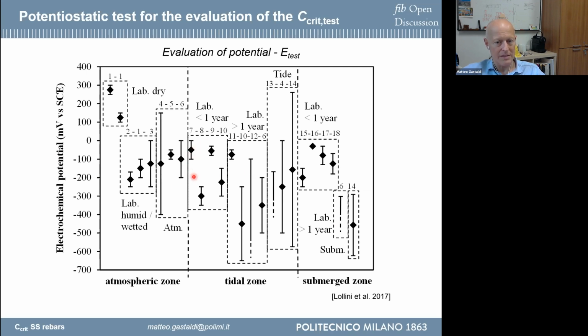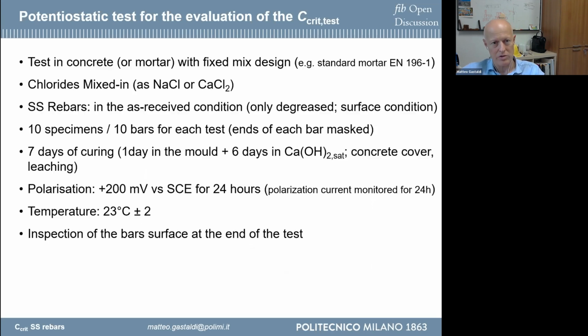We can analyze the data related to the potential on real structures, and you can observe that in a real structure, or also in a laboratory test, you can measure different potentials in different conditions: atmospheric area, tidal zone or splash zone, and submerged area. You can have different potentials, and if you move to the worst condition, that is the condition in which you have the higher amount of oxygen, you are close to 200 millivolts. And so this is the potential that can be considered to have an idea about the worst condition that you have in a real structure, in areas in which you have a high amount of oxygen.